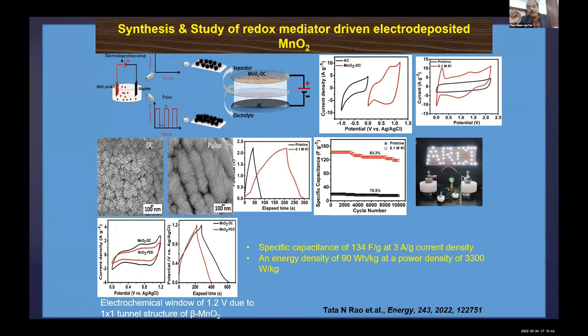And I am talking about equivalent capacity of non-aqueous capacitors, what we talked so far. The moment you have an aqueous electrolyte, you don't need to worry about firing. You just run the way you are doing your lead acid battery, and then I could go up to 10,000 cycles. The only thing is you need more numbers because your voltage is less. But that's what is happening in lead acid also. So we're trying to see whether we can equate to the lead acid with these supercaps, but with very high power, so that it doesn't die. That is the next one, and it is my students' work. But we are very happy with this.